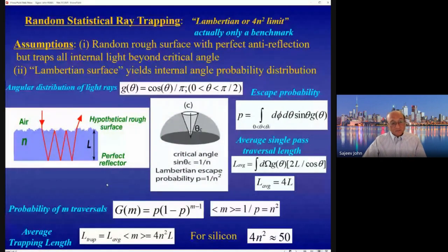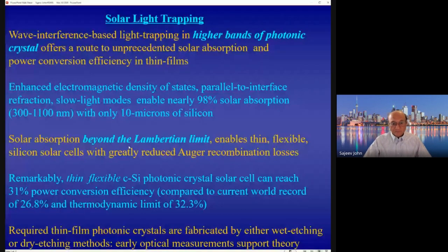And what I'll suggest is that with photonic crystal architectures, which treat light not as a ray, but as a wave, it is possible to well exceed this limit, this long-standing benchmark that has been used in the solar cell industry. So what I'll show is that with wave interference-based light trapping, using a photonic crystal, and in particular the higher bands of that photonic crystal, one has an unprecedented route to solar absorption power conversion efficiency using thin film structures which can cause this type of trapping.